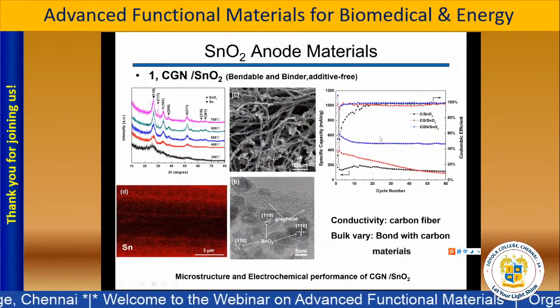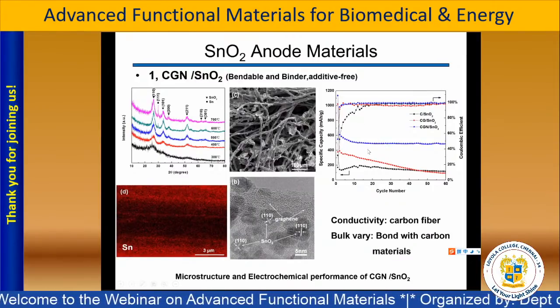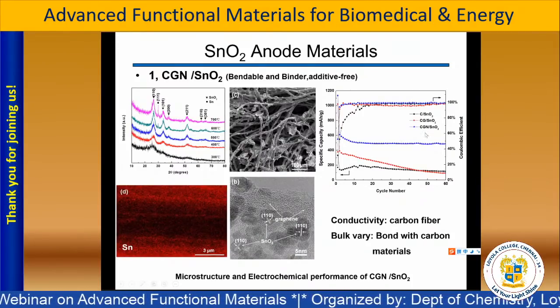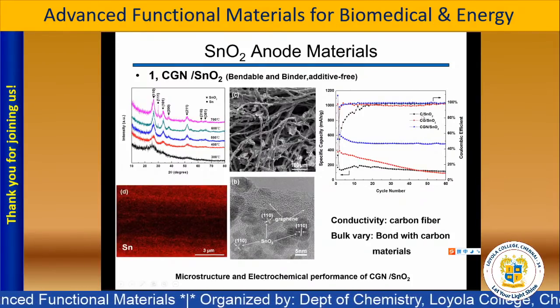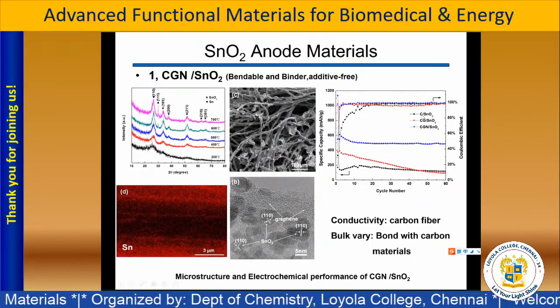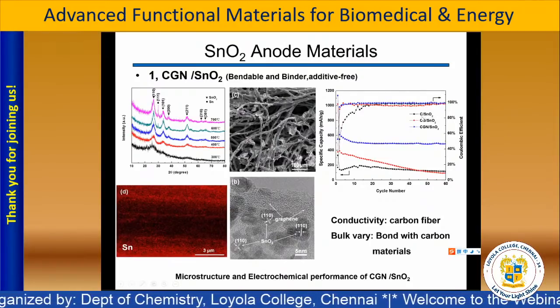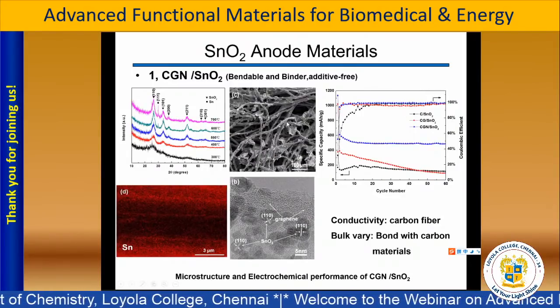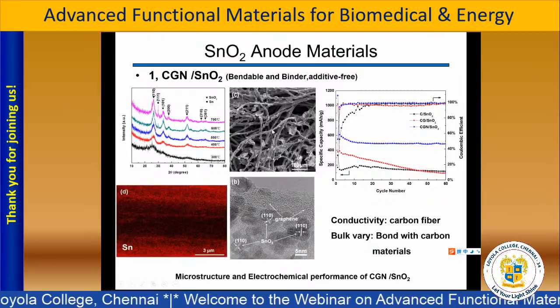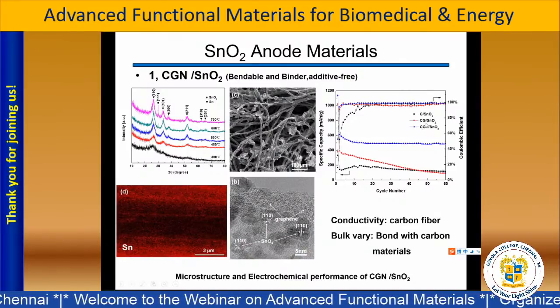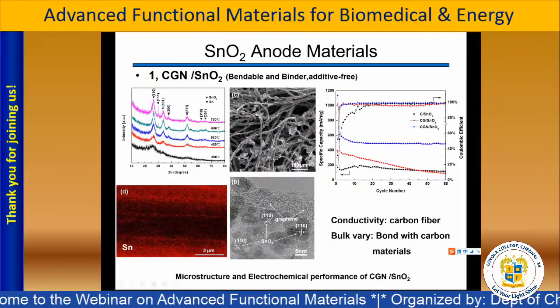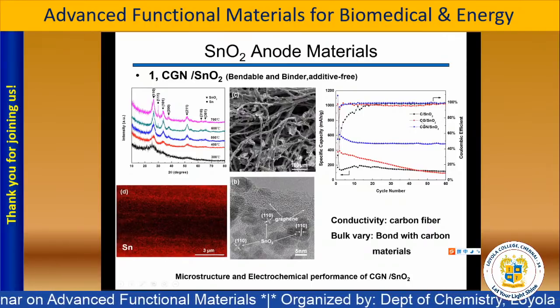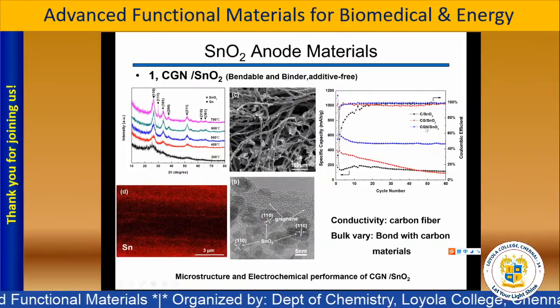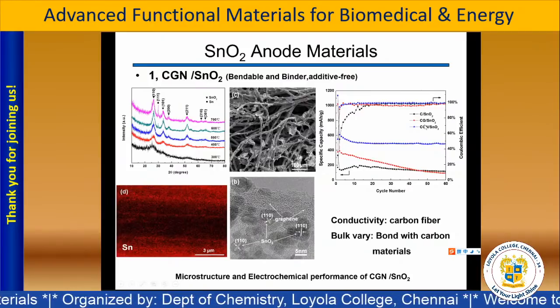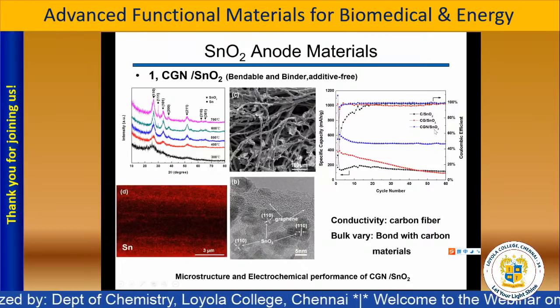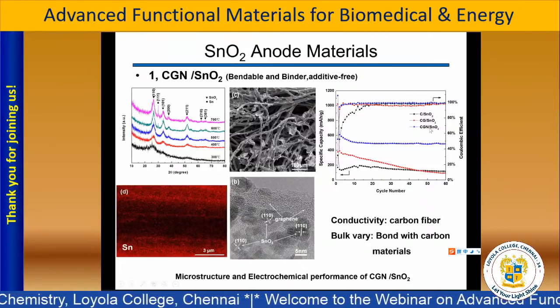So we tested the property of this material. We compared three kinds of material: carbon tin oxide, where we didn't put the graphene on the carbon fiber surface; CG tin oxide, where we use another polymer to transfer into the carbon; and CGN, where we use the graphene with the carbon fiber and then with tin oxides.